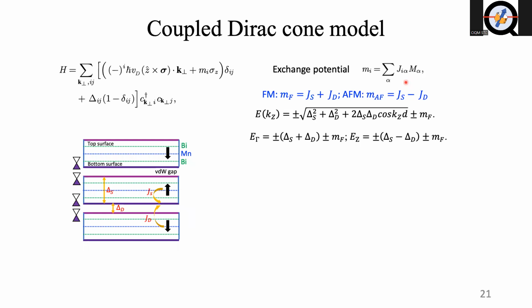In the anti-ferromagnetic case, can be written as JS minus JD. And from this model, we can write the E-k relation using those parameters. I can choose some high symmetry points by choosing kz equals 0, the gamma point, or kz equals pi over a to be the Z points. And then we know the energy at those specific high symmetry points as a function of those parameters delta S, delta D, or MF. Now, how are we going to extrapolate those parameters?